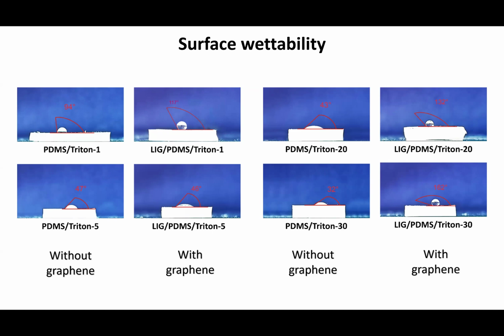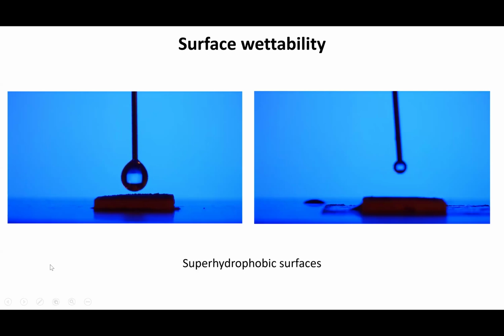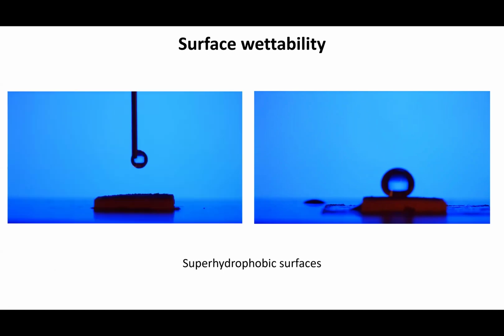It's a hydrophilic surface. Yet if you add graphene, you get a super hydrophobic surface. Your drop just stands like a sphere. And I think it's interesting to see how that looks in real time. Here we attempt to put a drop on the surface, and it's so super hydrophobic that the ball just rolls off. However, if you are really careful and you align your sample carefully and do everything super correctly, then you can get the sphere to stay, and you see the water just stays there. So this can have interesting applications in water repelling surfaces just by adding graphene.